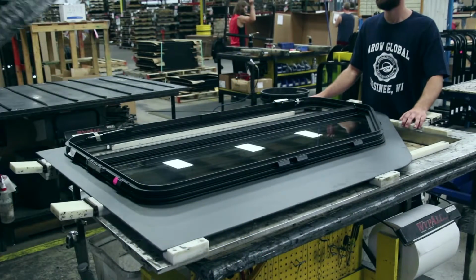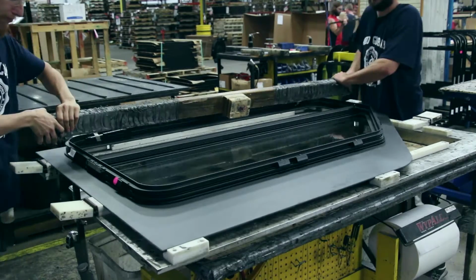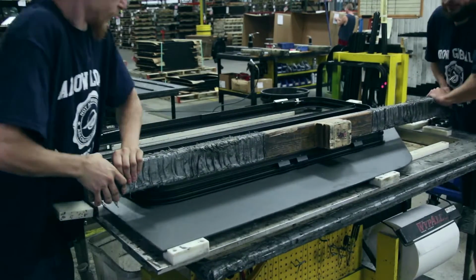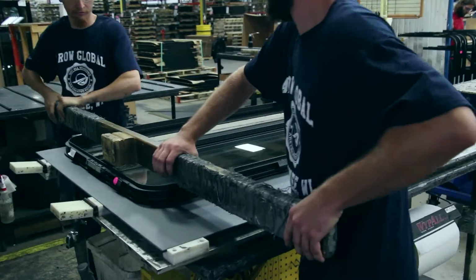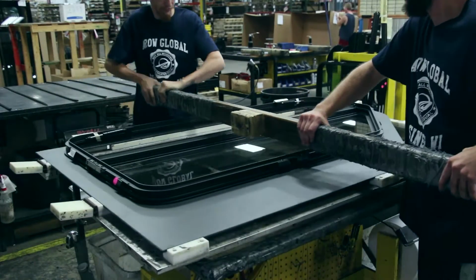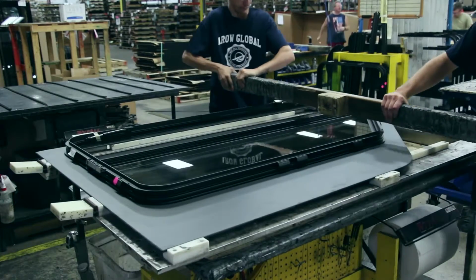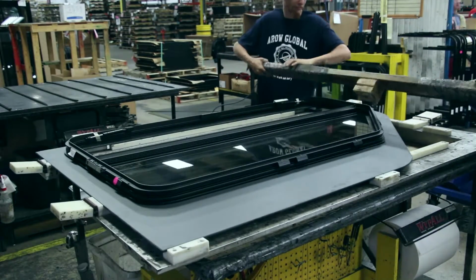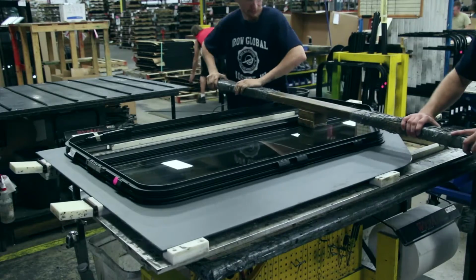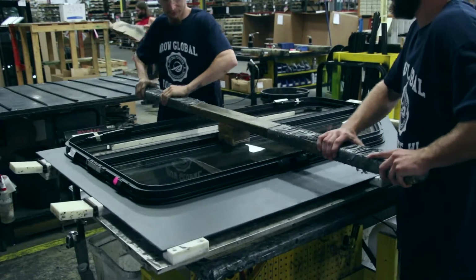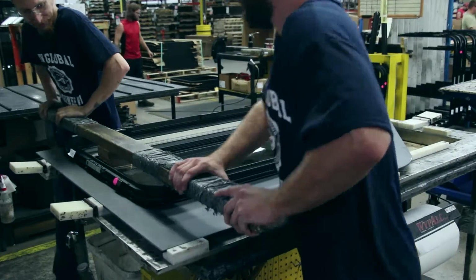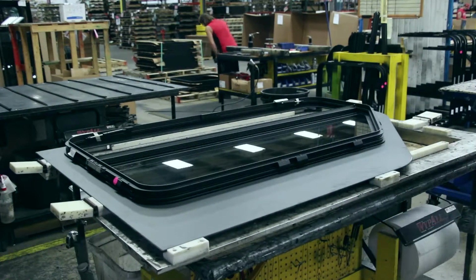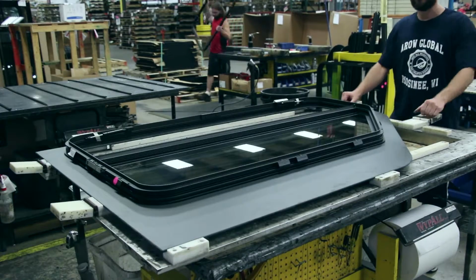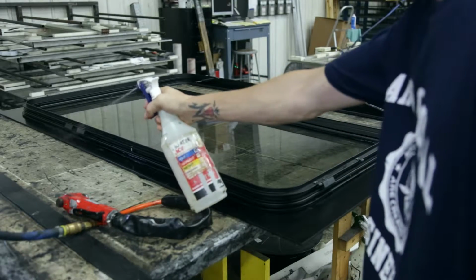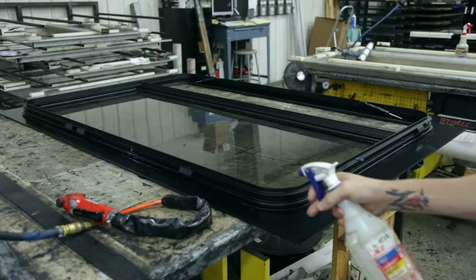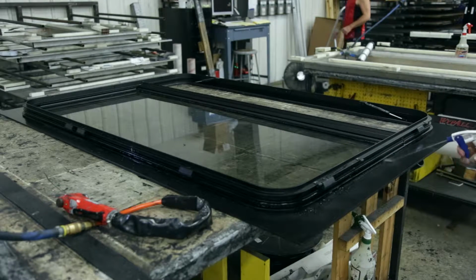Step 8. After the frame is correctly positioned, press down on the frame until it makes contact with the glass. This displaces the adhesive to achieve a bond thickness that seals the glass to the frame and ensures a durable joint. If the frame is not pressed into position, you may experience a leak, bond failure, or poor alignment with the exterior surface of the adjacent windows. If you overpress the frame, there is a risk that when you release your pressure the frame will relax, draw air into the adhesive, and reduce the strength of the bond. Step 9. Allow adhesive to cure for 24 hours before handling the window. Water can be sprayed on adhesive to promote curing.